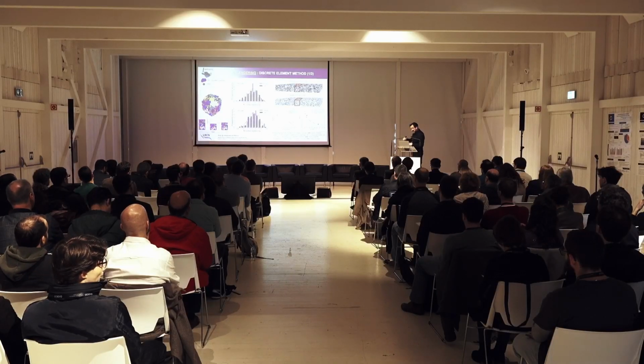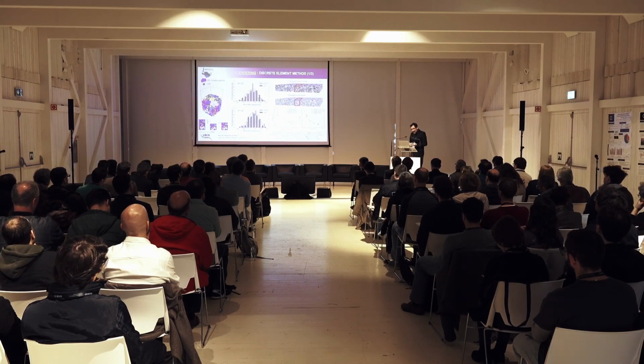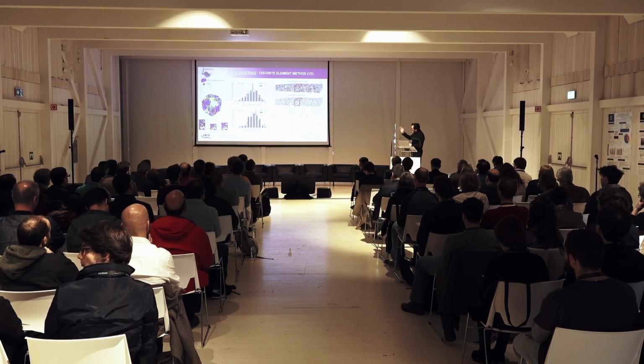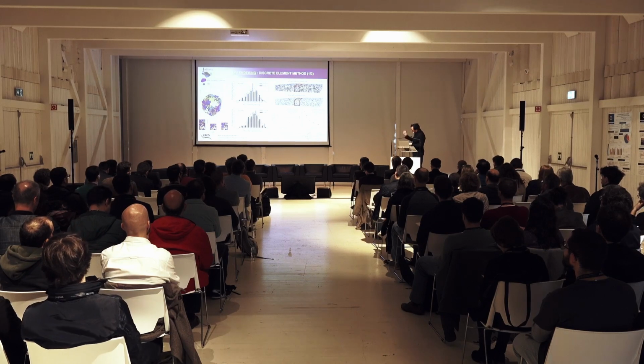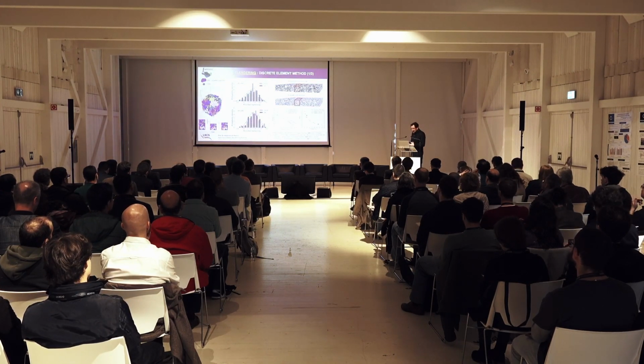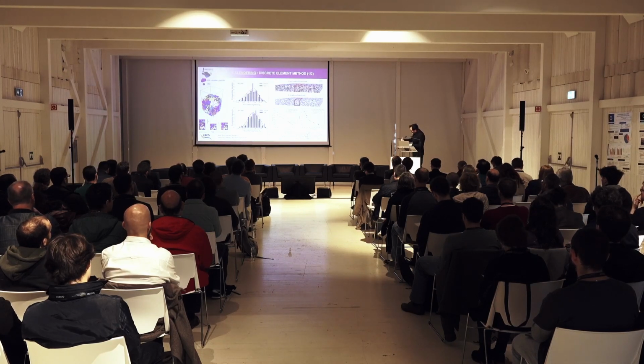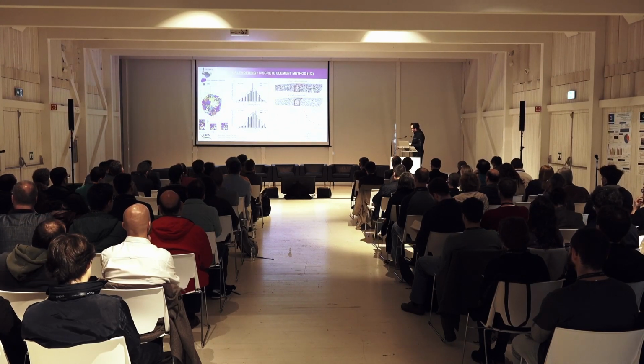Here we use the discrete element method. We use as an input the dry electrode microstructure. And here, this model also captures the impact of the calendering on the deformation of the active material particles that can eventually lead to cracking. It's something that we also want to avoid when we are producing these electrodes for battery applications.